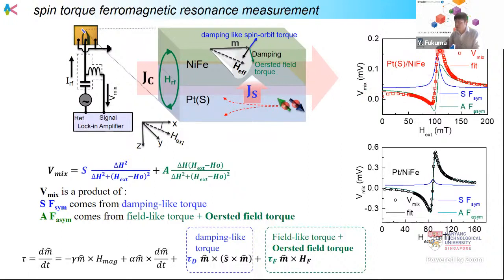This voltage is comprised of a symmetric part and an antisymmetric part. So we can get this kind of rectified voltage. The symmetric component is from the spin transfer torque. And there is also this kind of green antisymmetric component, which is mainly from the field-like torque. By comparing these two origins, we can estimate the charge to spin conversion efficiency.